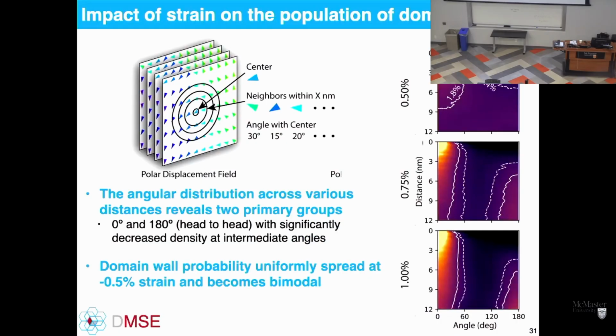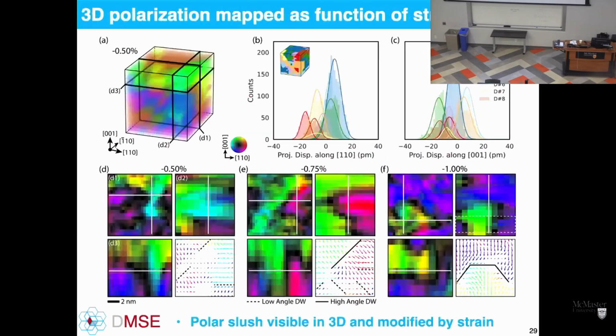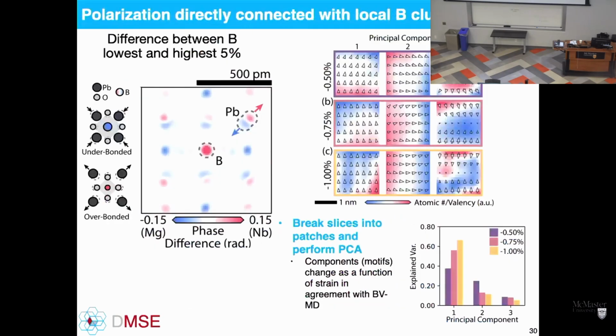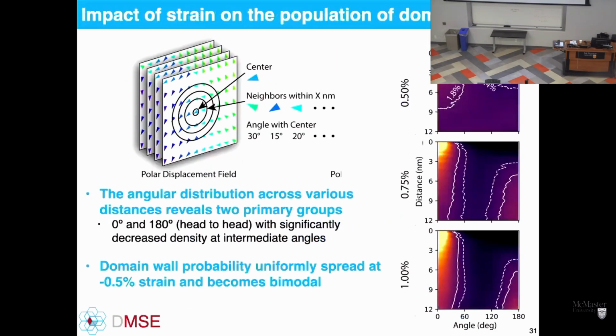Okay, so taking this a step further, we can do a lot of statistics over all these data sets that we have by looking at a correlation of angle map here. What we're doing is essentially looking at the neighbors in the neighborhood of a certain atom and looking at the correlation. And so for different angles, if I look at this 0.5%, what you would notice here is that there's a lot of polar disorder. As we go up in higher strain, more of the lattice is pointing in the same direction, right? You can see that visually, but now we can map that out statistically to understand and compare with theory. So these are our experimental results.